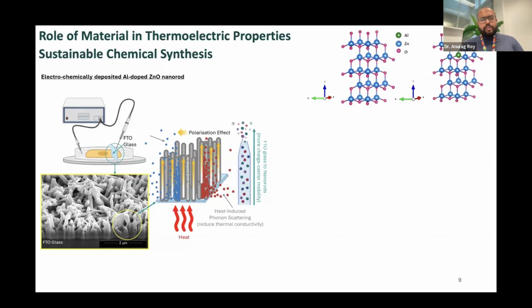And so due to this, if we supply heat, the heat-induced phonon scattering reduces the thermal conductivity, and also as it is deposited on the FTO glass, the charge carrier mobility is also accelerated. That's why we prefer electrochemical deposition, where the conducting substrate and the 1D nanostructure, the combination of both concepts, is there, and that ultimately helps to generate a high polarization effect and more electricity out of it.